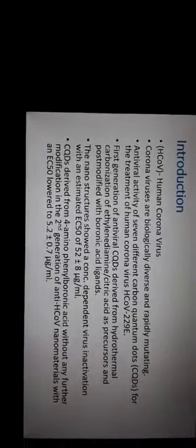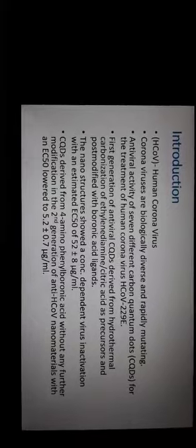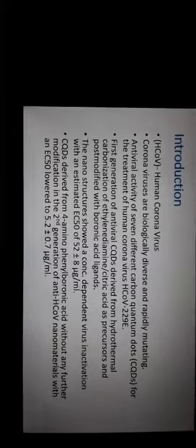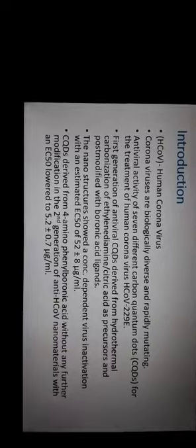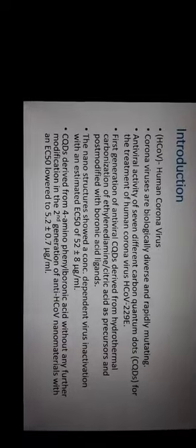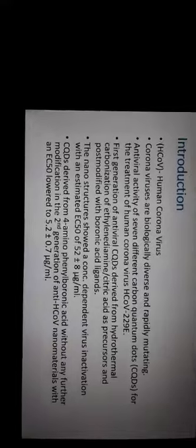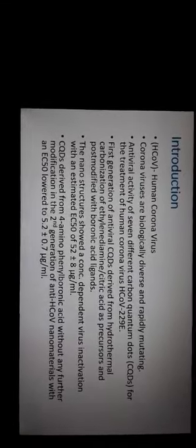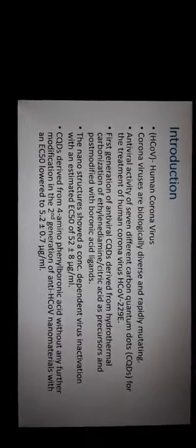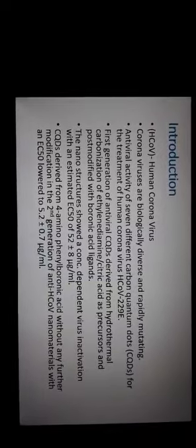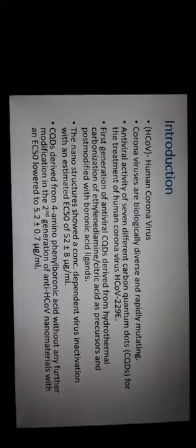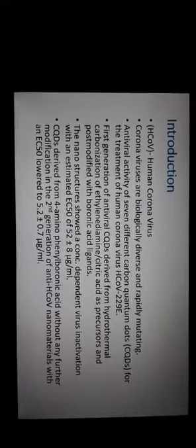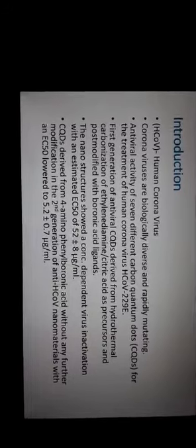So the first generation of antivirals of the carbon quantum dots, abbreviated as CQDs, were derived from hydrothermal carbonization of ethylenediamine or citric acid as precursors. And as I said, they were then post-modified with boronic acid ligands. Now these nanostructures showed a concentration-dependent virus inactivation with an estimated EC50, now by EC50 I mean the half maximum effective concentration, of 52 plus minus 8 microgram per ml.